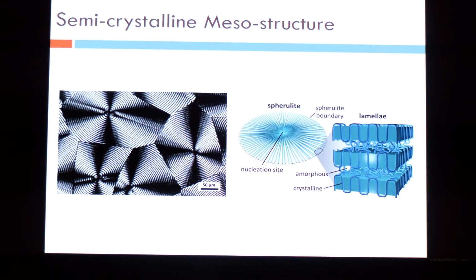And these lamellae will fold out from a nucleation center to form what you see on the left, which is a simple birefringent image of the polymer melt after it has solidified. And these are called spherulites. Okay? So you see these beautiful polymer crystals, but they are not really 100% crystals.